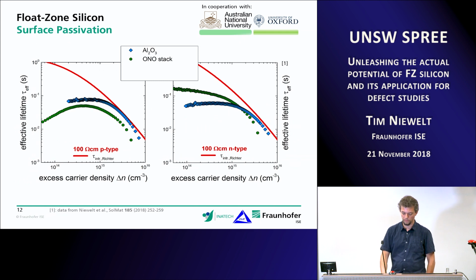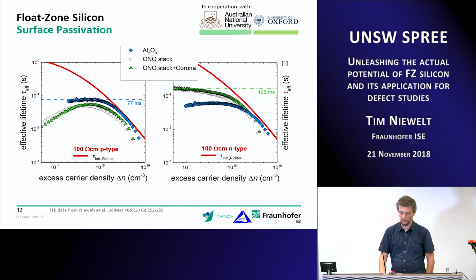What we've seen there is that, yes, we get pretty good lifetimes on our material. So here is the 100 ohm centimeter P-type and N-type silicon. As we would expect, the aluminum oxide works a bit better on P-type silicon, while the Ono stack is better on N-type silicon. That's related to the fixed charges that these passivation layers apply. Then we've seen a bit of improvement of the lifetime when we were using this corona charging on the Ono stack. That's what we expected, basically. And the lifetimes that we got out of this experiment on the stabilized wafers are among the highest that have been reached with these passivations and with these materials.